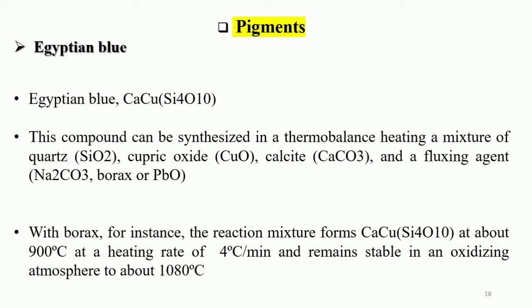With borax, for example, the reaction mixture forms CaCuSi4O10 at about 900 degrees Celsius at a heating rate of 4 degrees Celsius per minute and remains stable in an oxidizing atmosphere to about 1080 degrees Celsius.